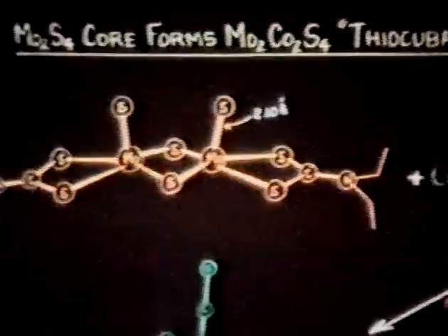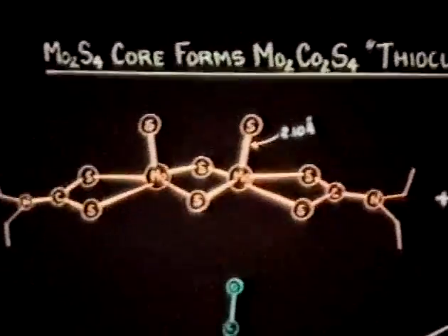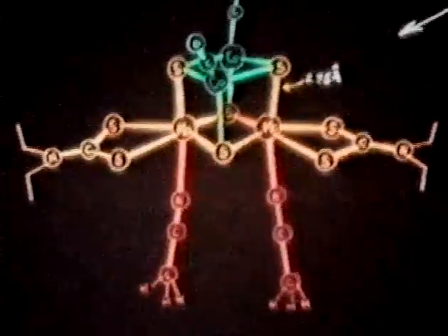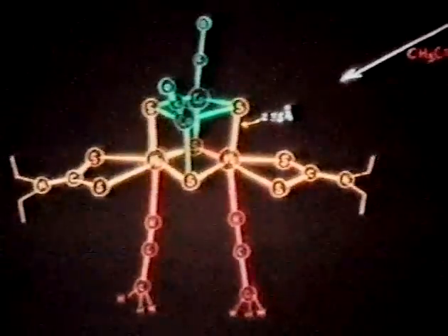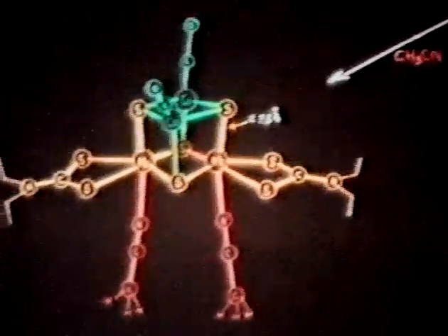Now, the interesting thing about this particular model is that what it does is open up these sites on the molybdenum here, so that the solvent molecule actually binds to the molybdenum, which it will not do in this molecule. So it's a suggestion that this is another way which cobalt, interacting in the way I said before, creates a site of molybdenum. Now, having shown a very specific model here with all of the questions about XAFS and so on, which I'm not going to answer today...